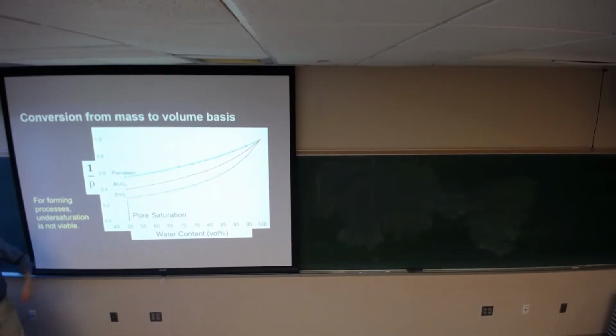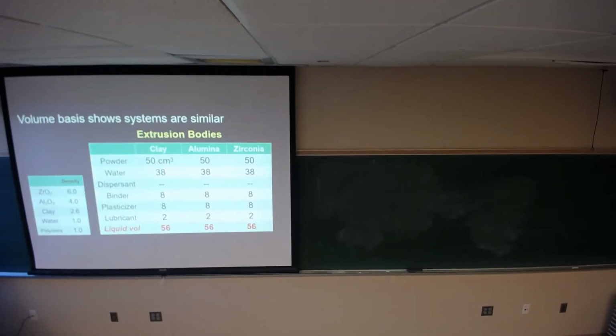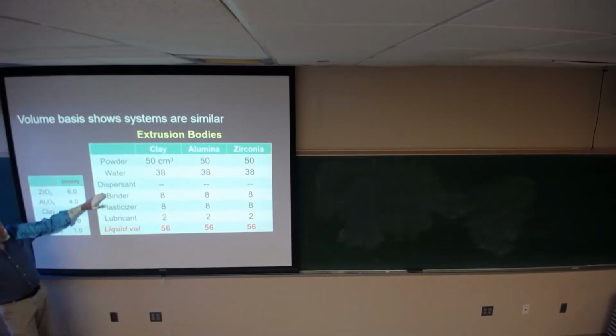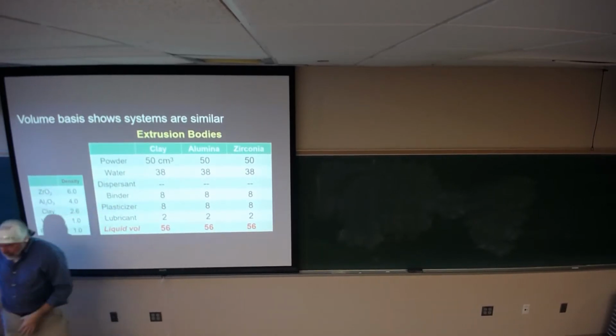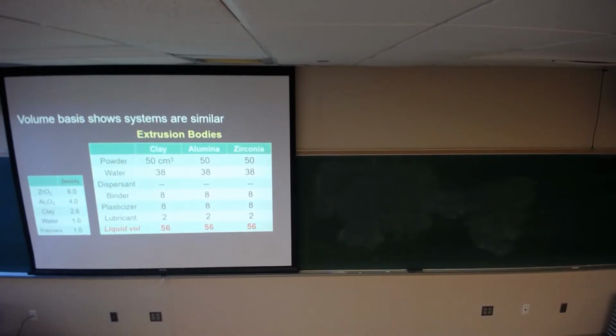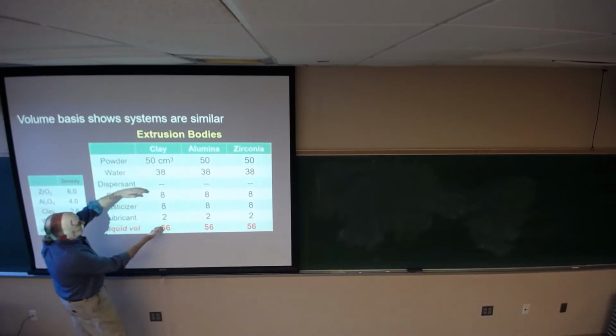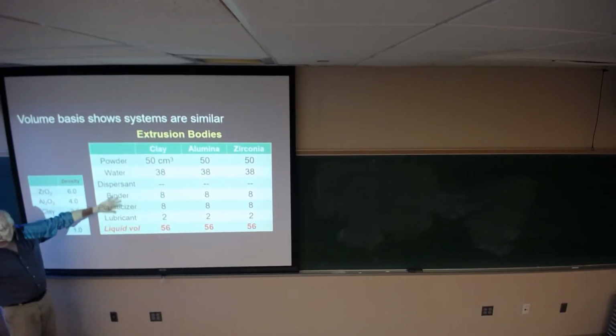So now what happens is that if I correct all the batch compositions for volume, this is what happens. Suddenly, those batches that looked so different now look exactly the same. So my amount of binder for alumina and clay and zirconia is the same. The amount of plasticizer is the same. And the lubricant and the extrusion body is the same. And my water contents are the same because the water content is dictated by filling the pore volume plus excess. So if you add up all of this, your polymers, your binders, etc., are all contributing to volume.